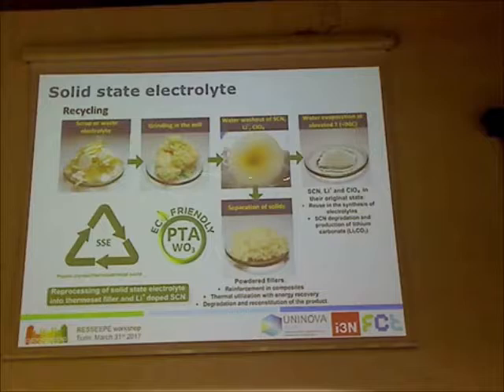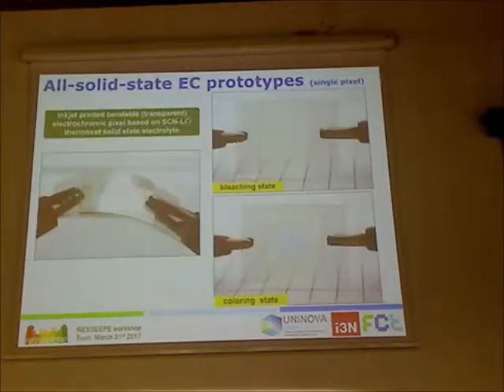Just one slide to talk about how we can also recycle these electrolytes: we can mill it, grind it, wash it to remove the lithium salt, and then separate the solid phase from the polymeric matrix. It can be used for other purposes, and we recover the lithium salt that can be disposed of in another way, or used as we wish.